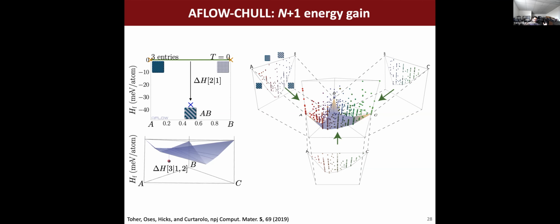And if we're looking at a quaternary system, they have to compete not only with the binaries, but also with the ternaries. So in order to be stable at higher numbers of compounds, you need to be even lower in energy than the compositions of lower dimensionality. Okay, so that increasing competition is very important.